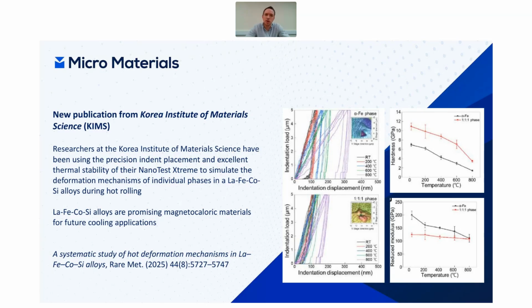But these are 5 millinewton indents, so at room temperature, it looks to be about 100 nanometers deep. Of course, the indents need to be sufficiently small as to be confined to within these phases. So they've been able to measure the hardness and the modulus as a function of temperature up to 800 degrees C in a high vacuum environment of these two different phases within these alloys.